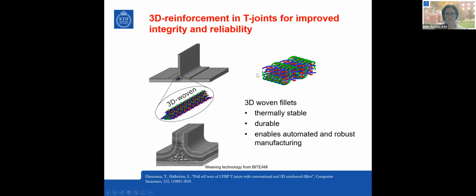What we have used it for lately is to fill the T-joint sections called the noodle area or the fillet area, which is normally filled with a roll of prepreg or something. These fillets have a tendency, when you don't do it properly, to crack by thermal contractions and differences in thermal expansion. And we have seen that if you instead use the 3D woven fillets, they become thermally stable, since you have fibers in all directions, so it doesn't move as much as if you had fibers in only two directions. It becomes more durable, and we can make an automated and robust manufacturing route.